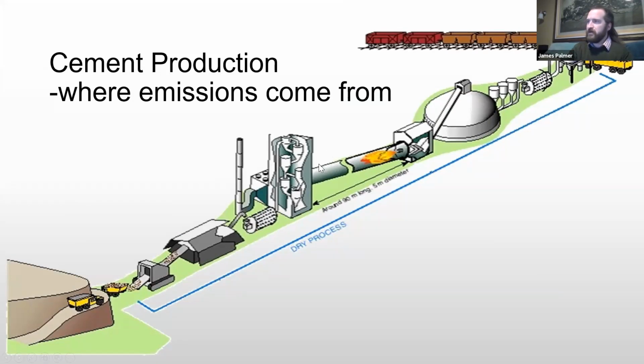But again, the biggest contributor to the CO2 is actually coming from this calciner tower that Marvin went into a little more detail on. Basically, as you cook limestone, which is calcium carbonate, CaCO3, the CO2 calcines and burns off and leaves this stack as CO2 gas. For every ton of clinker that you make, just over half a ton for each ton of cement is going to go out that stack as CO2. To make 1 ton of clinker, you have to burn close to 2 tons of limestone in the kiln, and that CO2 is released. So that is where PLC is able to make up that difference and reduce CO2 emissions.